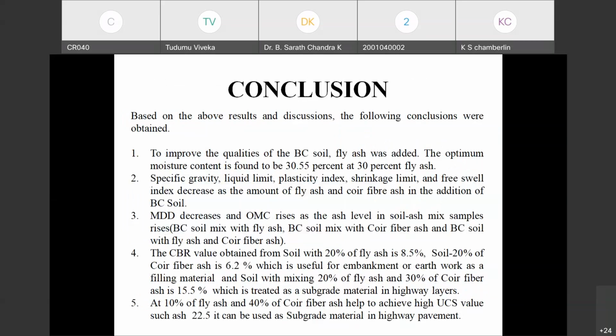Finally, it is the conclusion. Based on the above results and discussion, the following conclusions were made: to improve the qualities of the BC black cotton soil, fly ash was added. The optimum moisture content is found to be 30.55% at 30% of the fly ash. The specific gravity, liquid limit, plasticity index, shrinkage limit, and free swell index decrease with the amount of fly ash and coir fiber ash in addition to the BC soil. And next, the maximum dry density decreases and the OMC rises at the ash levels in soil ash mix samples.